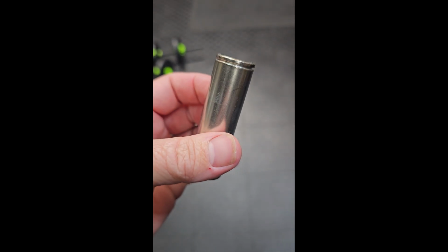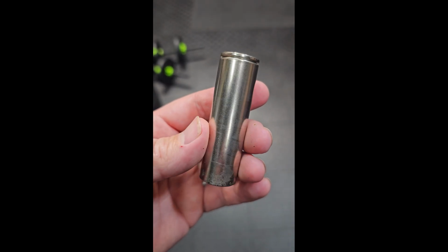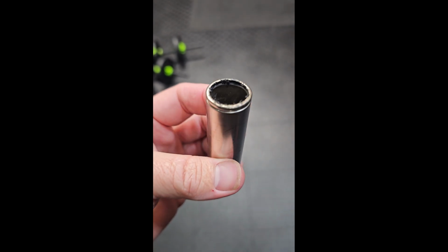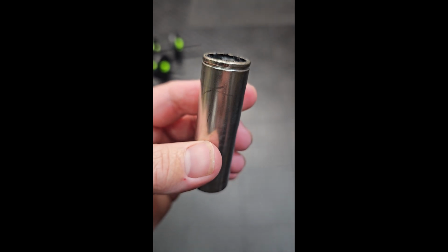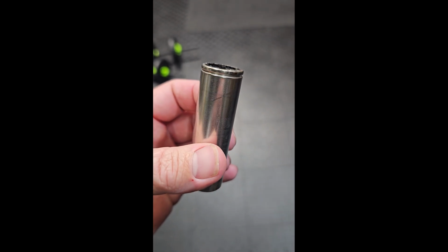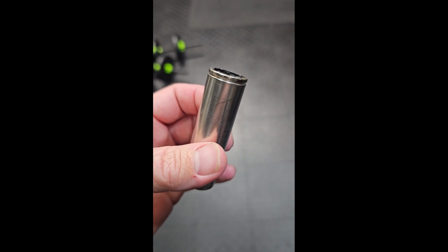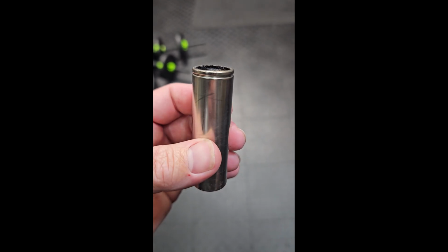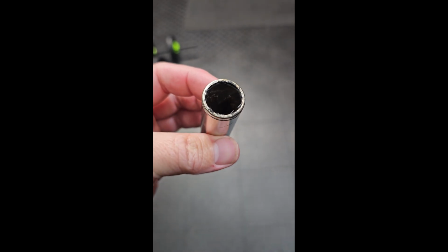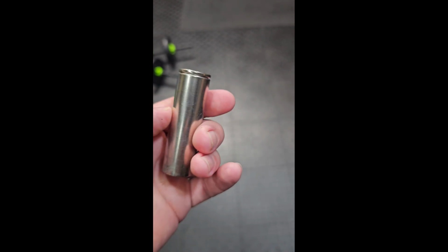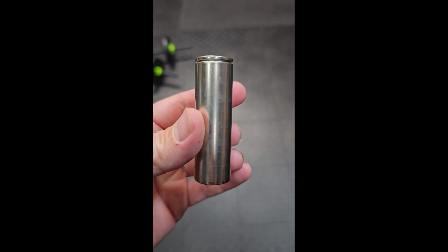Now it was at 3.99 volts. Maybe it would be a different story if we charged it up to 4.2 volts. But since it had corrosion on the top before, I didn't want to mess with it in case there was something sketchy going on, like it was leaking electrolyte from somewhere. But for this test, it did what it's supposed to do. It vented out the top, and yeah, looks good.